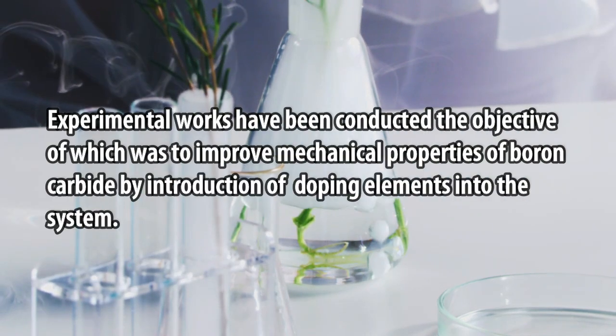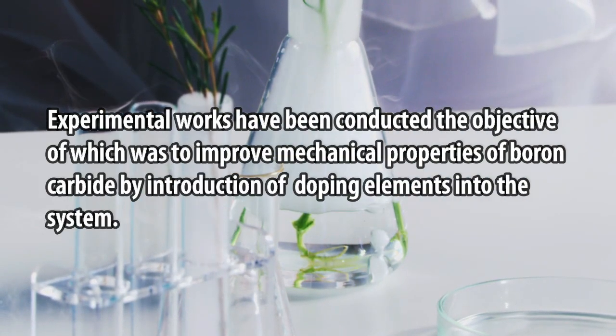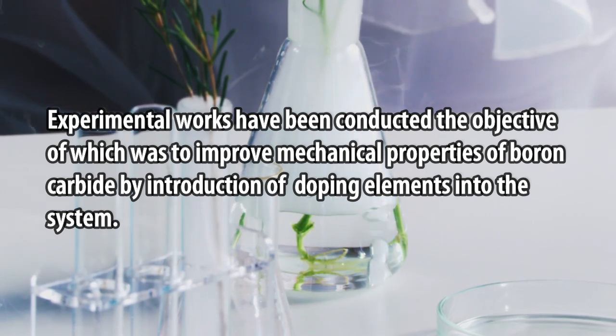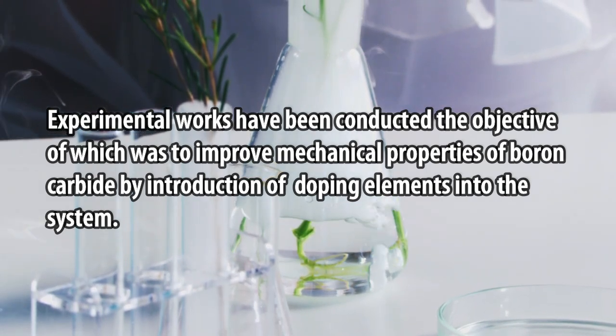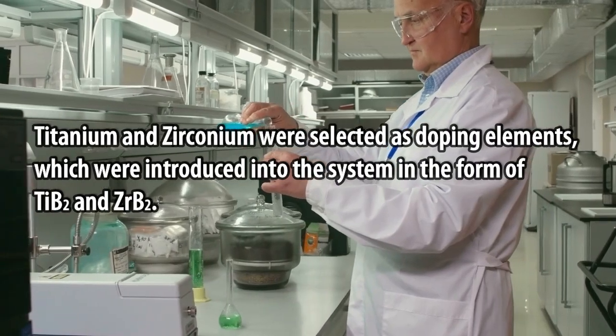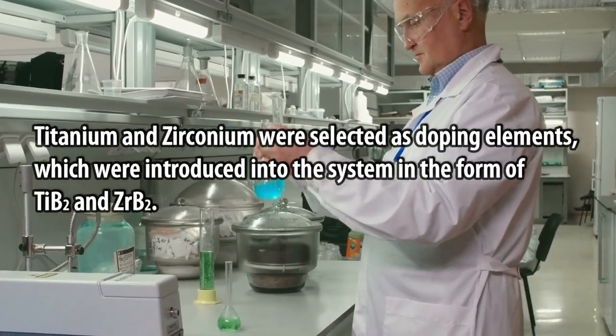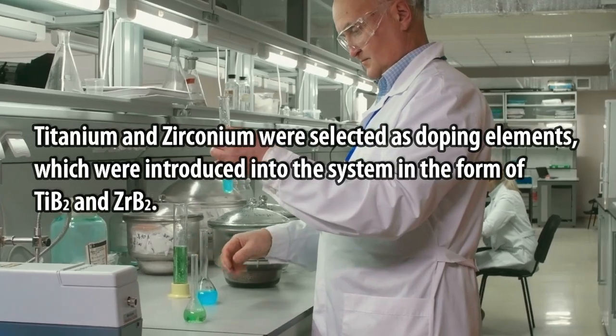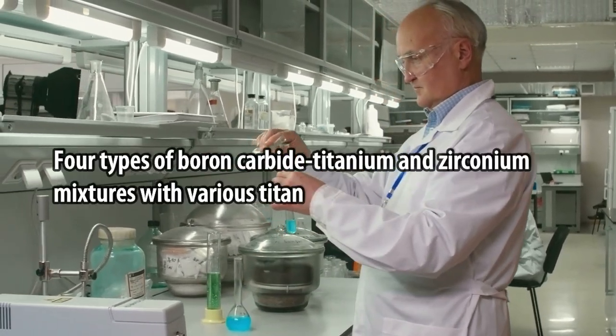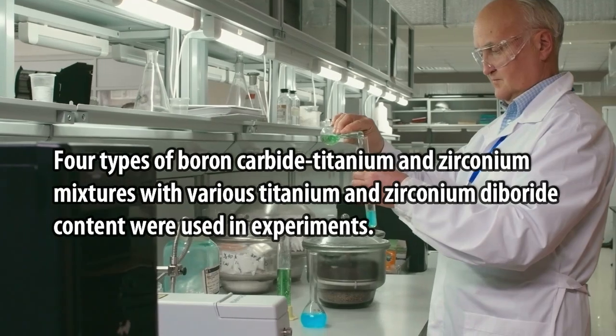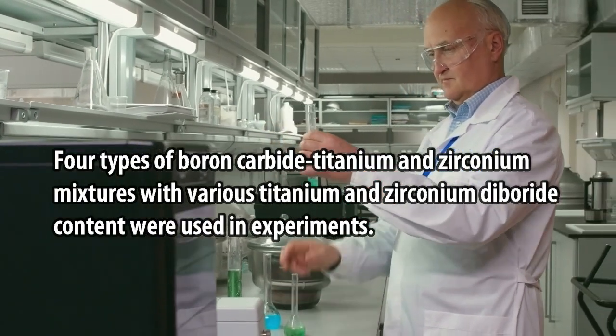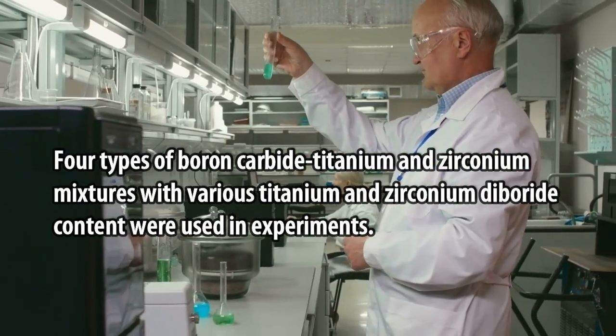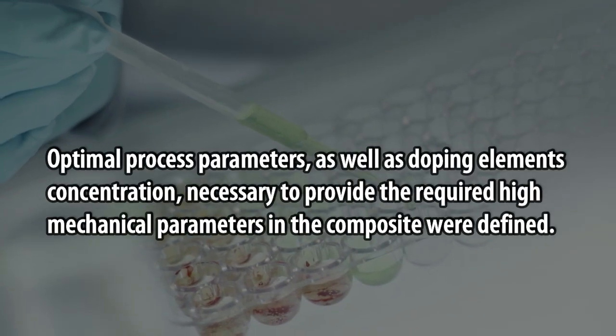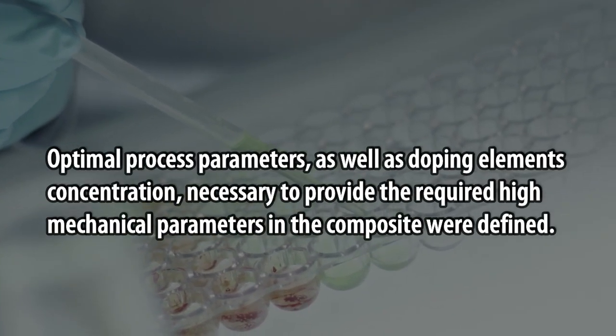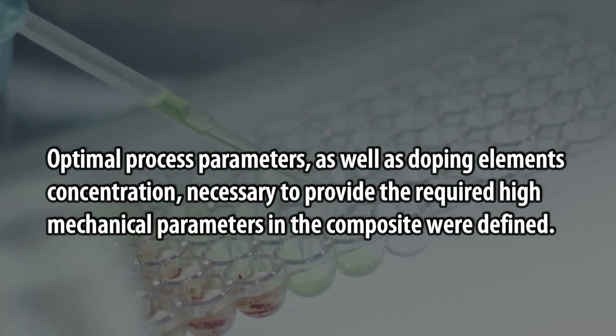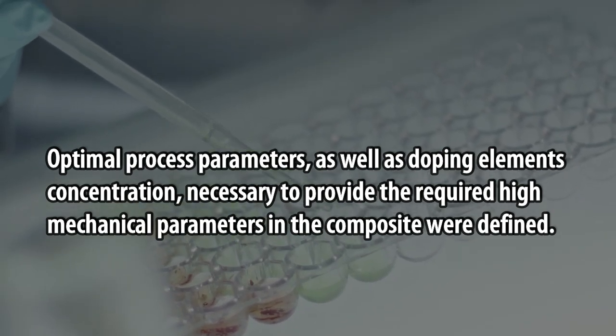Experimental works have been conducted, the objective of which was to improve mechanical properties of boron carbide by introduction of doping elements into the system. Titanium and zirconium were selected as doping elements, which were introduced into the system in the form of titanium diboride and zirconium diboride. 4 types of boron carbide, titanium and zirconium mixtures with various titanium and zirconium diboride content were used in experiments. Optimal process parameters, as well as doping elements concentration, necessary to provide the required high mechanical parameters in the composite were defined.